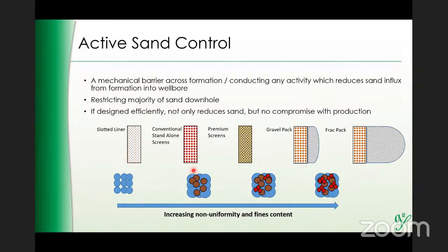And conventional standalone sand screens you can design if your sorting coefficient is less than 5 and your uniformity coefficient is less than or equal to 5. If you have premium screens, these are metal mesh screens, so these have a greater tolerance than your conventional wire wrap screens. In these screens, you can go with less than 10 uniformity coefficient and design a screen for that. Anything above that, if you want to control sand downhole, is gravel pack.